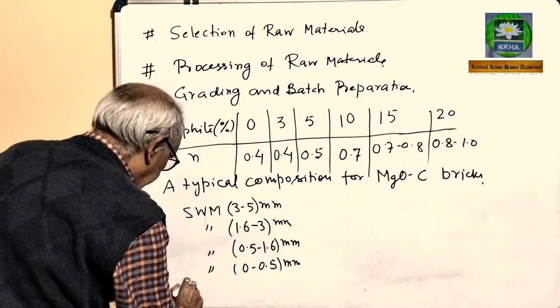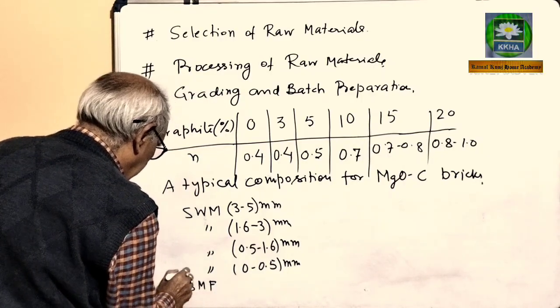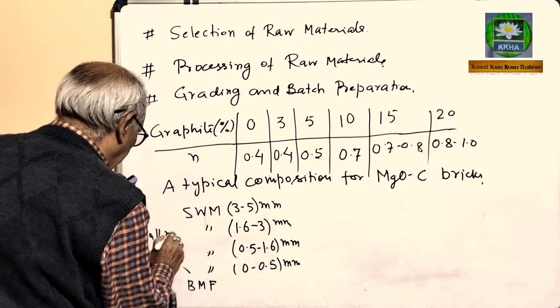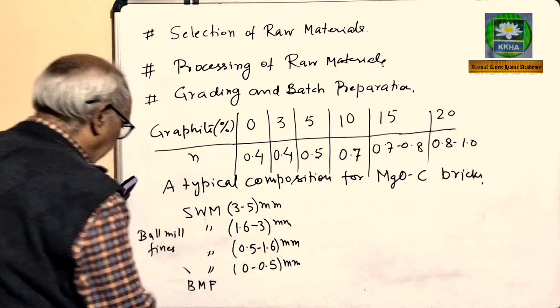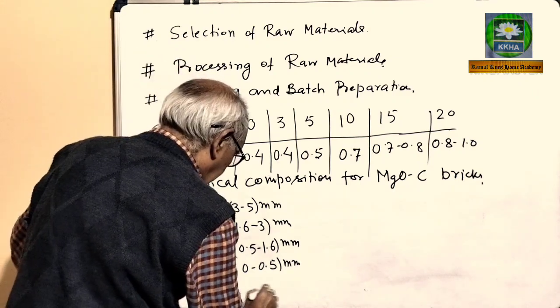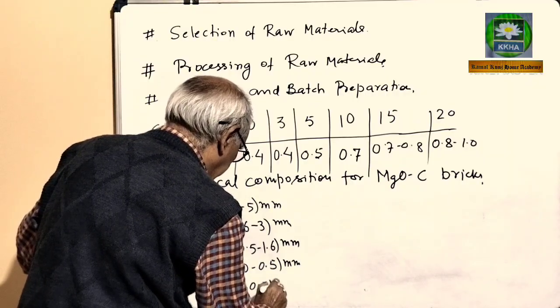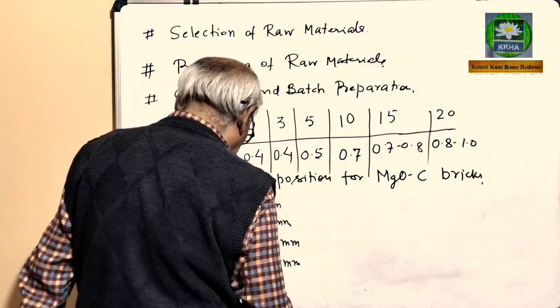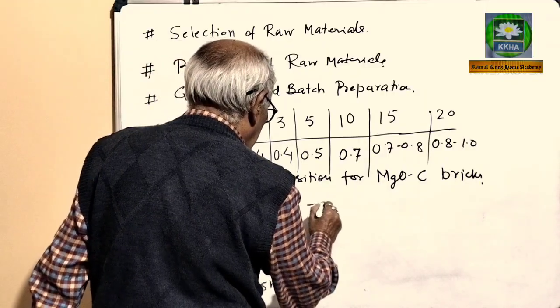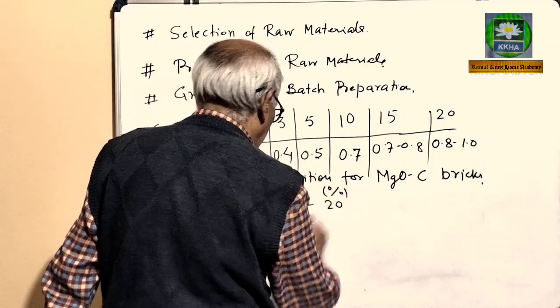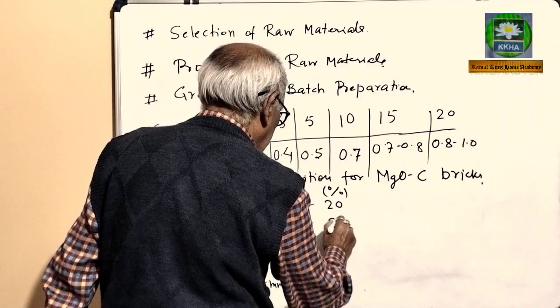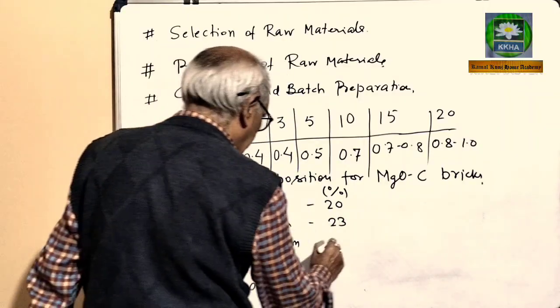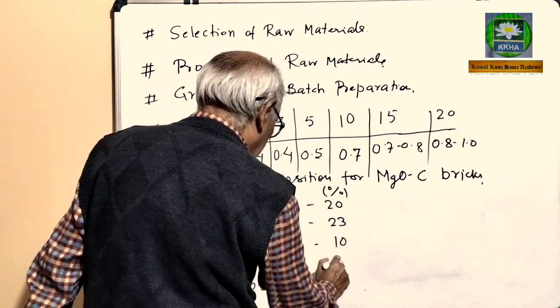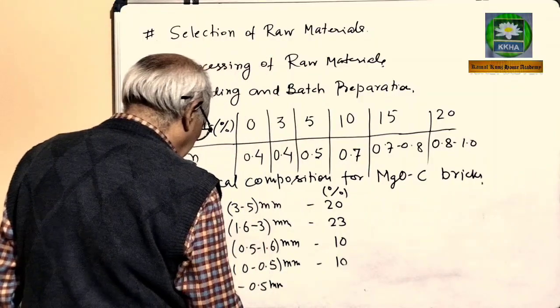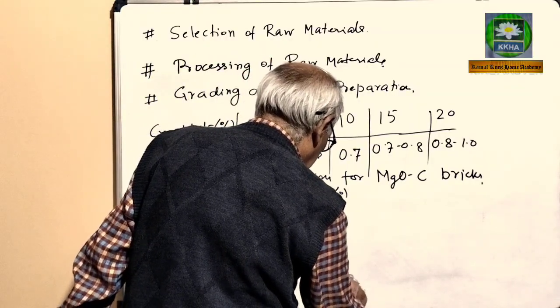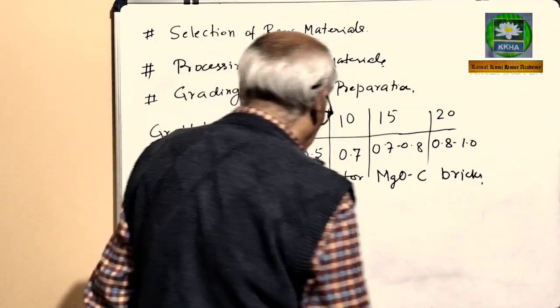and then ball mill fines. This is ball mill fines, minus 0.5 mm. So this should be around 20%. This fraction should be 23%. 0.5 to 1.6 should be 10%. This also 10%, and ball mill fines 25%.